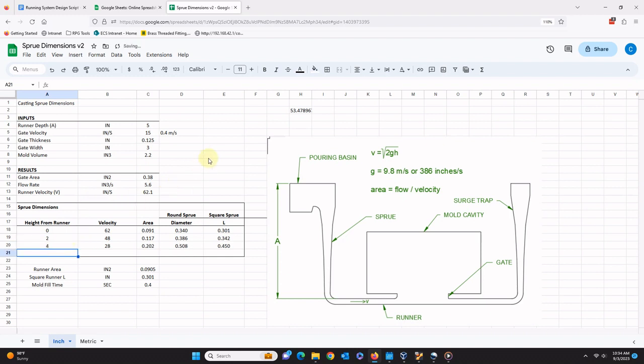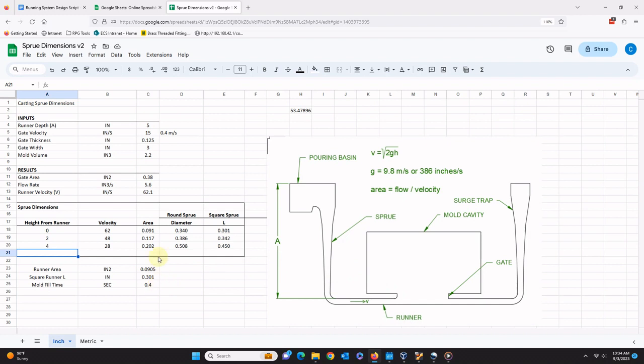The spreadsheet also calculated the fill time for the mold cavity. To clarify, this is a theoretical time from when the metal first enters the cavity to when it is full. In practice, there will be additional time to fill the running system first, and the flow rate will decrease some as the level in the mold cavity rises. A lower fill time reduces the chances of the metal freezing before the mold is filled, reduces temperature differences within the mold, and can help with shrinkage issues. In general, the lowest practical fill time is best. This is accomplished by using the largest gate that is practical.